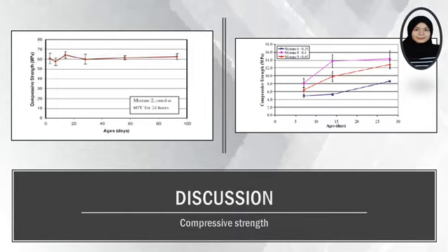Figure 2 shows that Hardjito et al. reported that with the increase of activator content, and consequently increasing the activator to fly ash ratio up to 0.4, the compressive strength of the resulting geopolymer mortar increased. However, increasing the activator to fly ash ratio to 0.45, there was a decrease in the compressive strength of the geopolymer mortar. This was possibly due to excess OH concentration, which consequently decreased the strength of the geopolymer mortar.